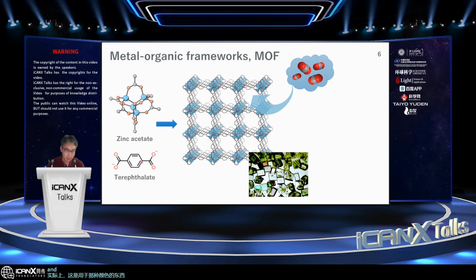You can also see terephthalate, which we use for PET bottles. Terephthalate has the capability to form a coordination bond to metal, which is shown in blue. If we combine the two, the carboxylate group will replace the acetate, and then this carboxylate coordinates to the zinc. Of course, terephthalate also has another carboxylate here. So by bridging between the metals with these organic molecules, we can have a quite extended and uniform structure as shown here.